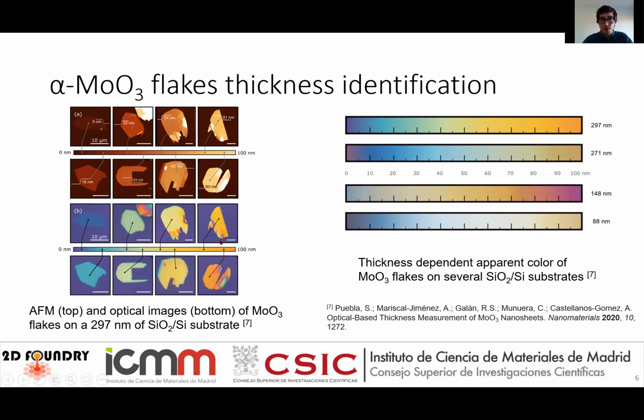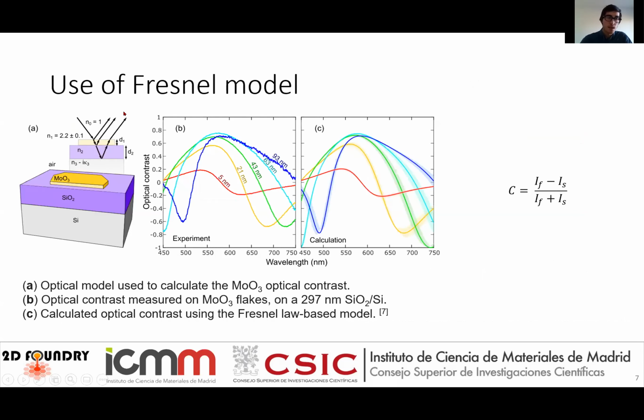And depending on the apparent color, you can use these color bars. These bars are from 88 nanometers of silicon dioxide to 297 nanometers of silicon dioxide. So it has different colors for different substrates. And you can use these color bars to identify the thickness in a fast way with an uncertainty of ±3 nanometers. But also, you can see in this image a physical model. I'm using a Fresnel model with a spectrometer coupled with the optical microscope. You can measure the reflectivity intensity in your system, and you can calculate the optical contrast.